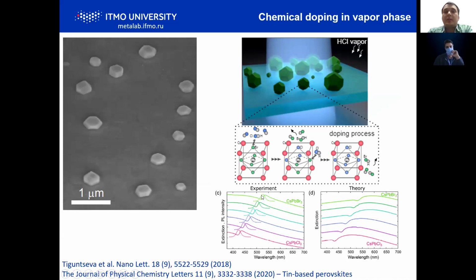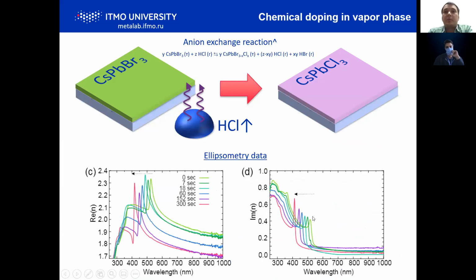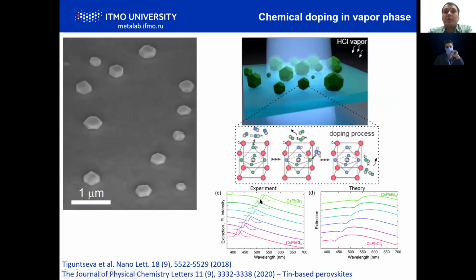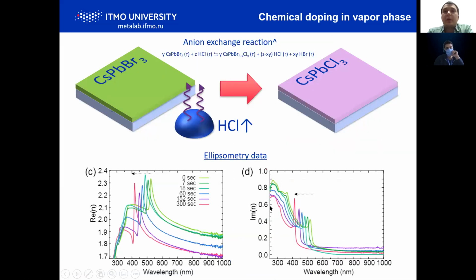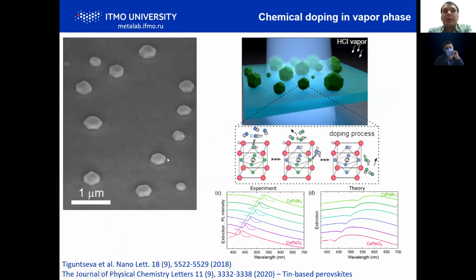And you see in the place where we should have maximum absorption, we have minimum because of the Fano dip. So this is quite important knowledge for people who want to create LEDs based on some nanoparticles. They should be careful because in extinction, standard spectrophotometer experiments with such substrates, they can face this problem: in the place where they should have maximum absorption, they have minimum. This is because of scattering, coupling of Mie resonances with excitons. This is quite useful knowledge.